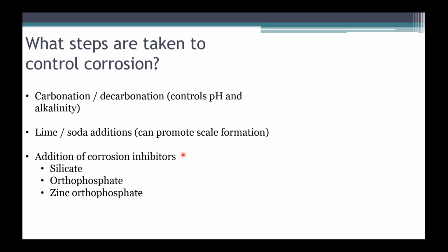Okay, now it may seem a bit odd that a drinking water facility would add phosphate when it's known to be such a problem for water quality at the other end, at the wastewater treatment facility. But this is becoming more common, and the recommended dosages are quite high. They're in the range of 1 to 3 milligrams per liter of phosphate, okay? And I'll talk a little bit more about that later on as well.